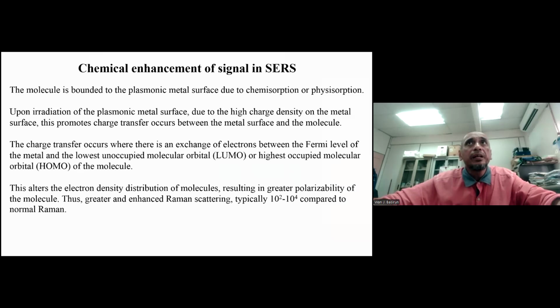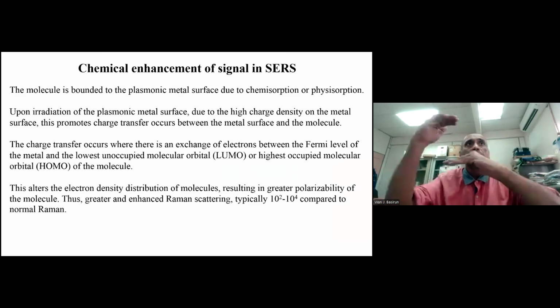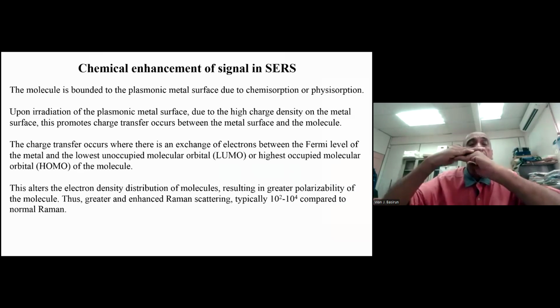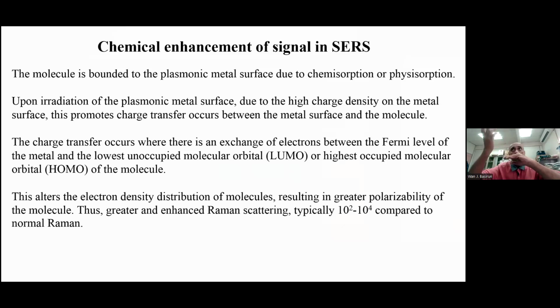Okay, so chemical enhancement. In SERS, the molecule must be bound onto the gold or the silver surface. So when the molecule is bound to the plasmonic metal by chemisorption or physisorption, and the laser radiation irradiates the molecule on the metal, then you get a charge transfer. This charge transfer is from the metal surface to the molecule. So the chemical enhancement is due to the charge transfer from the metal surface to the molecule.